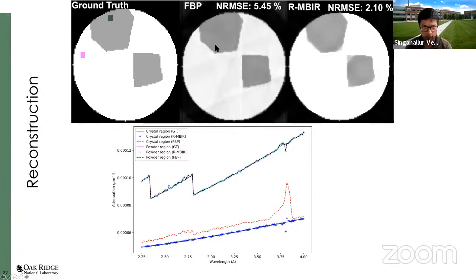Okay, so once again, we've shown that we can get some high quality reconstructions. Here is a cross section from the ground truth. Here is a filtered back projection reconstruction. And here is a reconstruction using the proposed model-based approach. And this is the reconstruction as a function of wavelength. On the top, you have two different regions. The outer region doesn't have any crystals, and these are the single crystal regions. In the single crystal region, the filtered back projection can result in very large errors, and it's visible from the quantitative metrics as well.